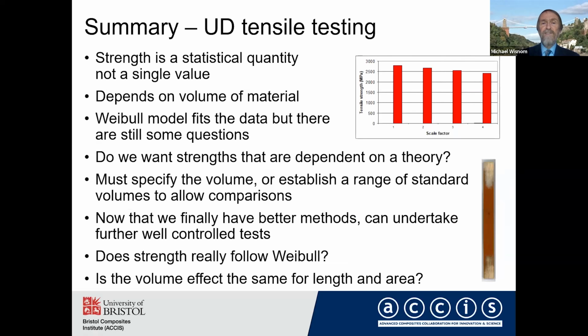A Weibull model seems to fit the data, but there's still some questions about that. It doesn't necessarily fully answer all the questions, even though the data I've shown seems to fit it quite well. But then there's another question: do we want to have strength values that are dependent on the theory? I could quote a Weibull mean strength, a Weibull characteristic strength, and a Weibull modulus, but do we want to have values which actually depend on the theory, which may not be fully accepted? And I think that the answer to that is probably no.